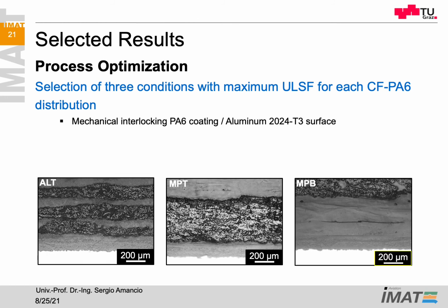With the analysis, and here, if we go for some detailed microstructure characterization, what you have here in white is the aluminum part. The aluminum part was sandblasted in advance to increase the surface roughness, and then here the different distribution of fibers. So there was a visual mechanical interlocking between the polyamide 6 coating and the aluminum. So if we draw an imaginary line here, we have the coating layer, and here the first, let's say, unreinforced layer from the composite part.